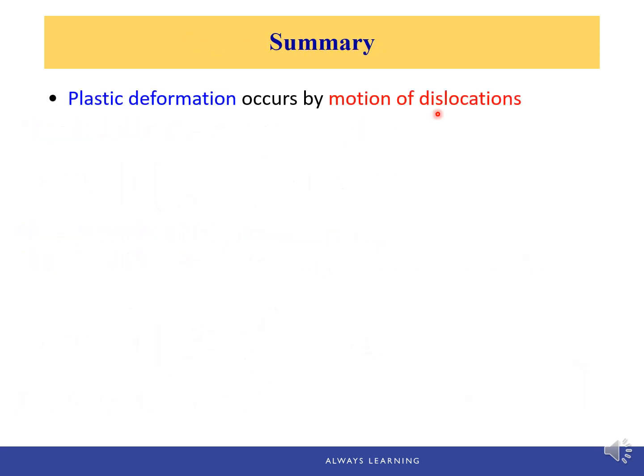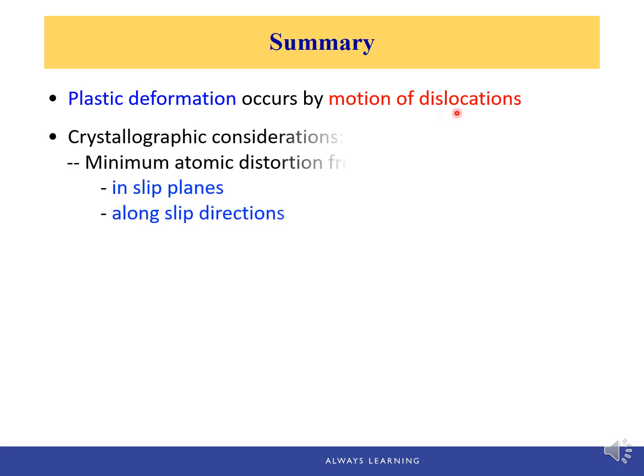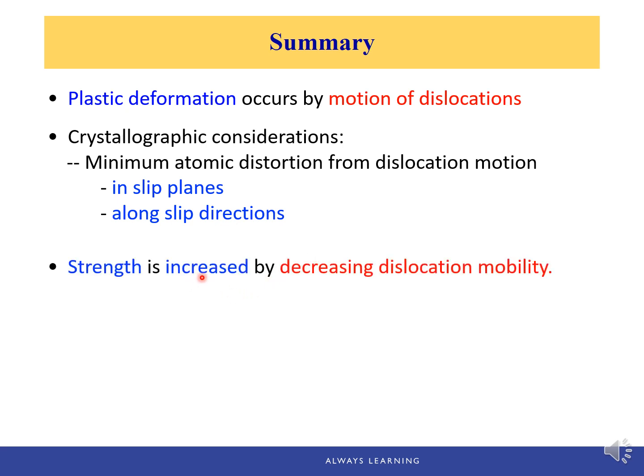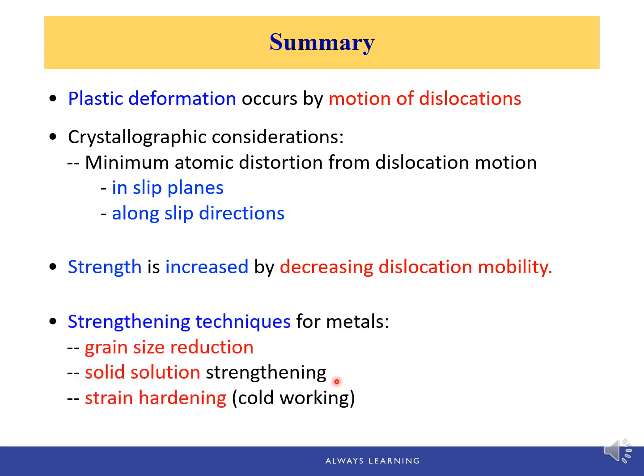So in this chapter, we learned that plastic deformation occurs by motion of dislocations. And dislocations move in the slip planes along slip directions. Those planes and directions are usually the most close-packed planes and directions. Strength is increased by decreasing dislocation mobility, and the strengthening mechanisms include grain size reduction, solid solution strengthening, and strain hardening, also called cold working.